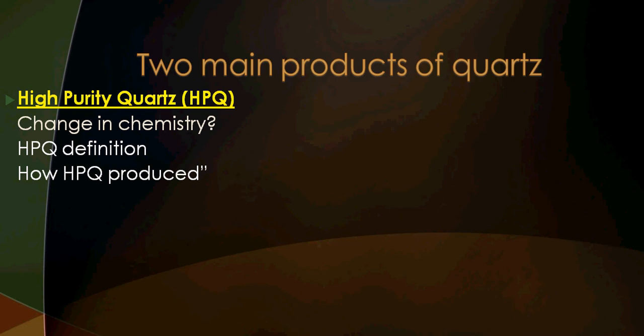High purity quartz is produced by intensive processing of natural quartz. We remove iron, we remove all other impurities by crushing, grinding, screening, magnetic separation, froth flotation. The processing is very intensive.